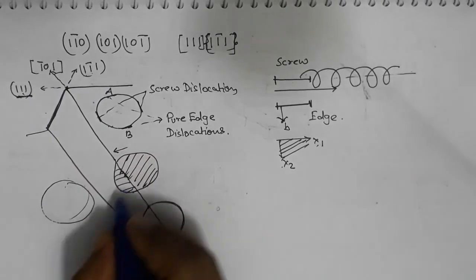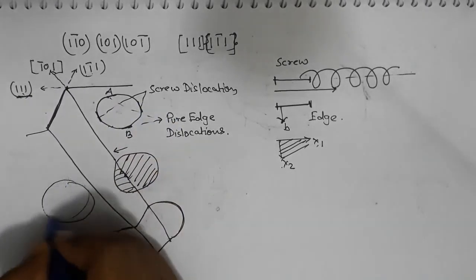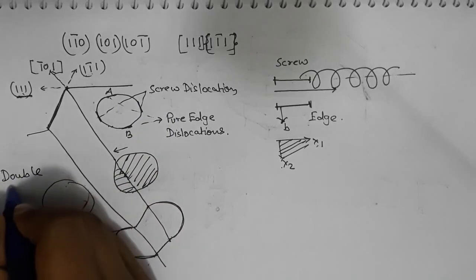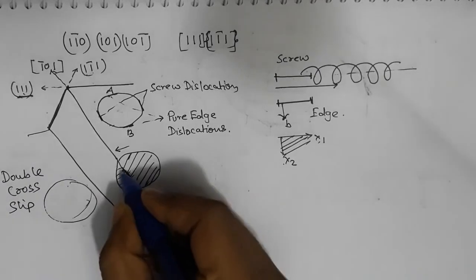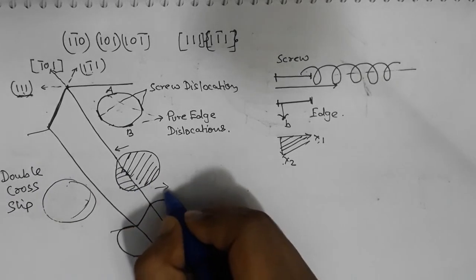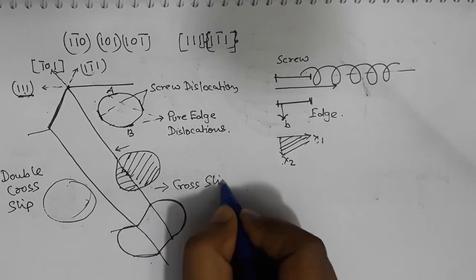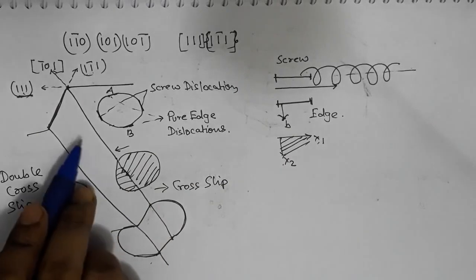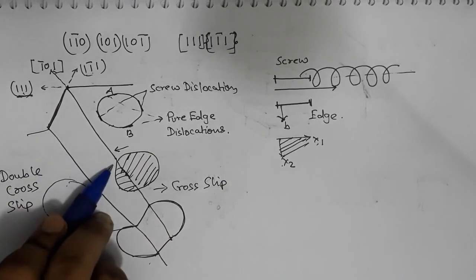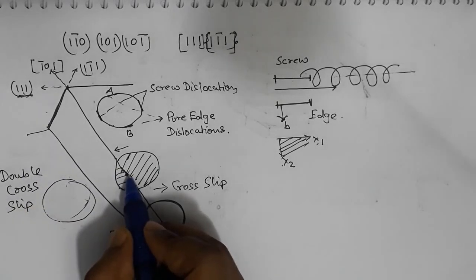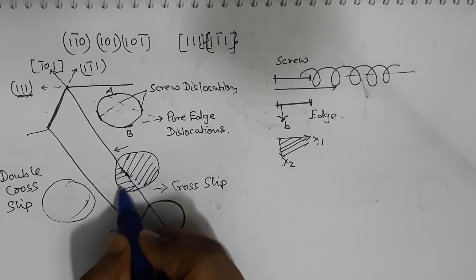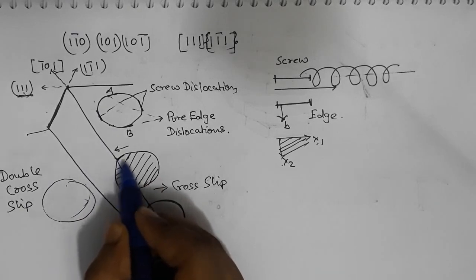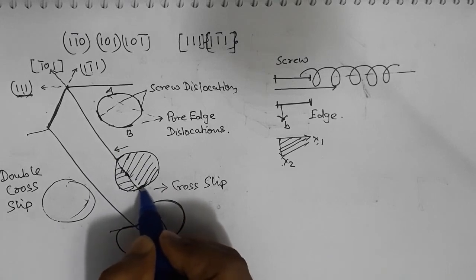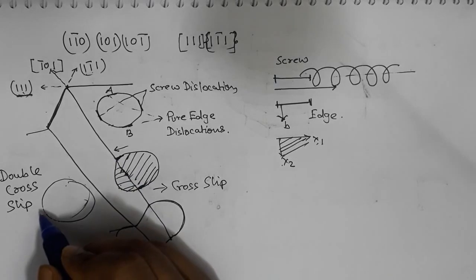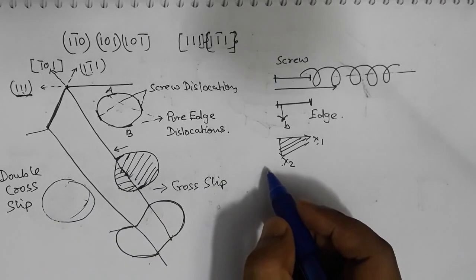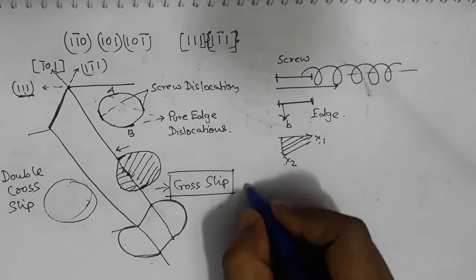And this phenomenon, when this whole dislocation loop moves here, is called double cross slip. And when it moves from this plane to that plane, that is called cross slip. I have tried to explain cross slip a little bit here, but the phenomenon is more complicated. It's just that the screw part of the dislocation needs no barrier, no plane, so it can actually just go there. The edge part of the dislocation will not be able to go. So there has to be something here so that the whole thing passes on, and this requires a little more explanation, which we will do later on.